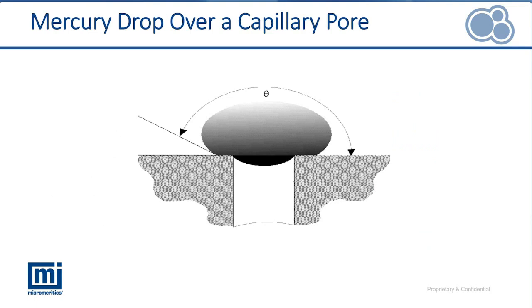Here we see a droplet of mercury sitting over an open pore, and we see the definition of the contact angle. We see that the contact angle basically is measured below the sample, where the mercury is in contact with the sample, and then the leading edge of the mercury. So contact angles for non-wetting liquids are greater than 90 degrees.